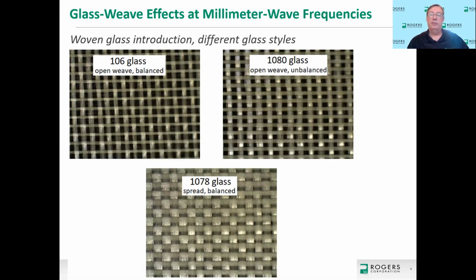And a spread glass does not have openings between the bundles, or what little openings are there, they're extremely small, usually less than a mil. So it's acting more like a uniform plane of glass. And that's the difference of some of these basic glass styles that are used for thin laminates. So these three glass styles are very thin glass styles and very often found in thin laminates. And of course, thin laminates are typically used at millimeter wave frequencies.